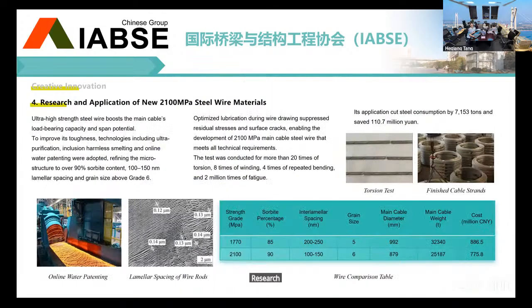Research and application of new 2,100 megapascal steel wire material. Ultra high strength steel wire improves the main cable's load bearing capacity and span potential, and its toughness. Technologies including ultra purification, harmless smelting, and online water patenting were adopted to refine the microstructure to over 90% sorbite content, 100 to 150 nanometer lamellar spacing, and grain size above grade 6.